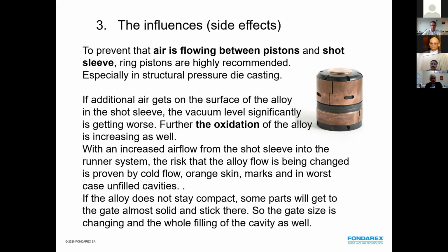The metal will remain, because aluminum in liquid condition is 2.55 kilograms per cubic decimeter. So it is not possible that a real vacuum is sucking. But if there is too much air, it will have an influence on how the metal gets towards the gate.